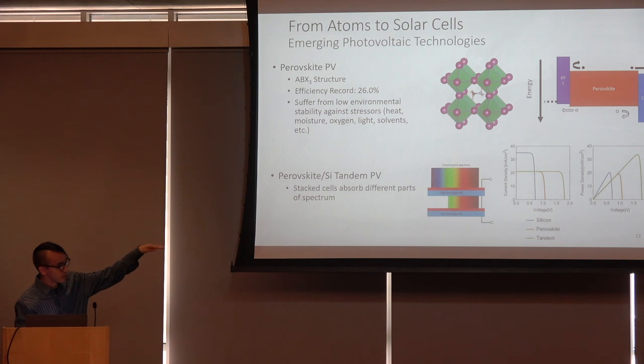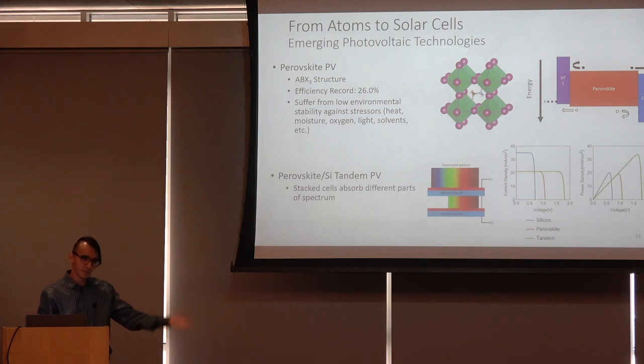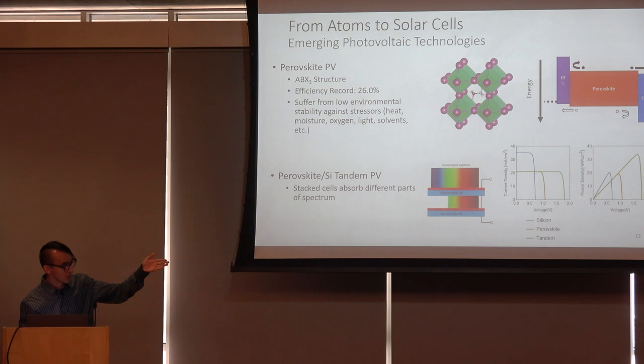And as you can see from the JV curves, the current from the tandem is fundamentally limited by the current that can be produced by the lower current device. But the voltage that you can get out is essentially doubled, particularly if you're connecting them in series, as what is known as a two-terminal tandem. And then if we look at the power curves, there is a very significant boost in the power generated by the tandem device as compared to the silicon and perovskite devices.